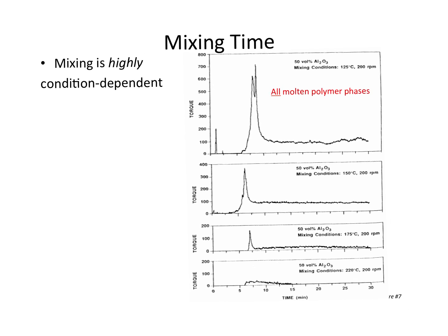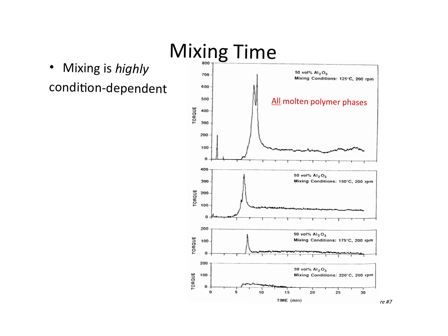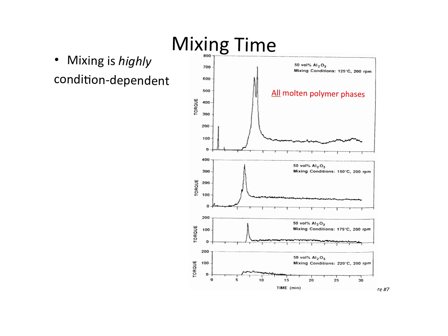And so the mixing process in all of this is highly condition, I'm sorry, concentration as well, dependent. And what I've got here are four plots, all of which start with two constant things. 50 volume percent alumina, all right, which you now know is actually not that challenging in the scheme of things. It's not 70 or 80 percent volume alumina. And we're also at 200 RPMs. All right, those are the constants through all four of these plots. And we're working with polyethylene, which, depending on molecular weight, melts at kind of the lowest condition on this. So here are 125, 150, 175, and 220 degrees C. So we have the same polymer, same alumina, same RPMs associated with this process, and same total solids content.